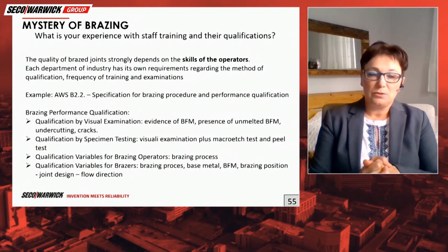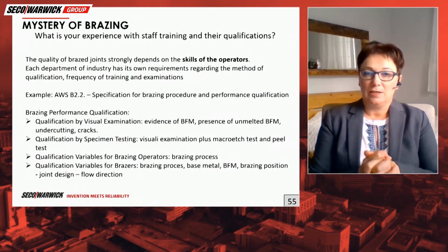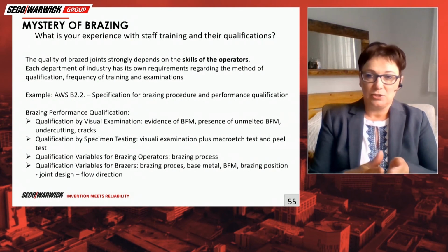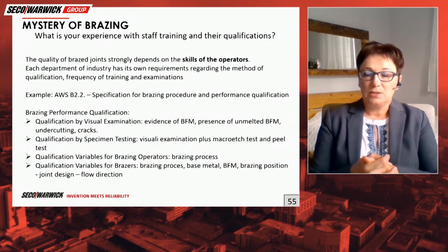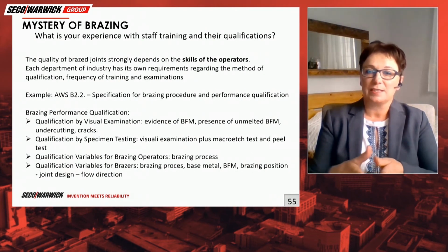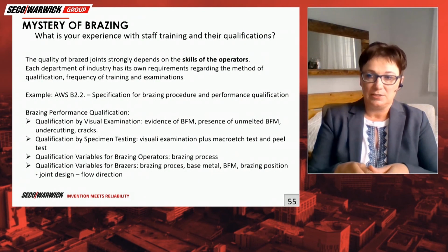Peel test we use to evaluate the coverage, the filling of the joint. So this test will also show internal discontinuity, internal voids, pores, cracks, inclusions, and level of coverage.